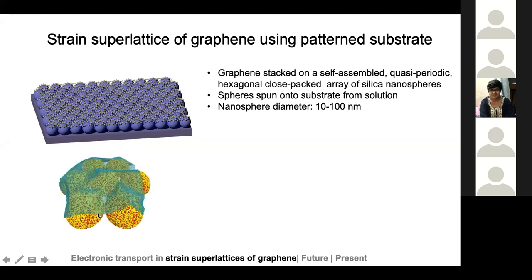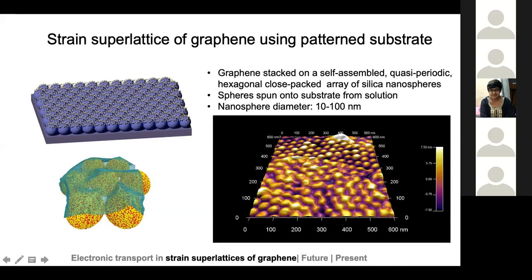So what happens is, as the graphene settles down on top of the nanoparticles, it stretches in those regions which are in contact with the top of the nanospheres. So these regions will have more tensile strain while it remains suspended in the middle region. And hence you have created a varying, a non-uniform strain superlattice in your graphene layer, which has a hexagonal closed packed structure. So this is an atomic force micrograph of one of my actual devices.